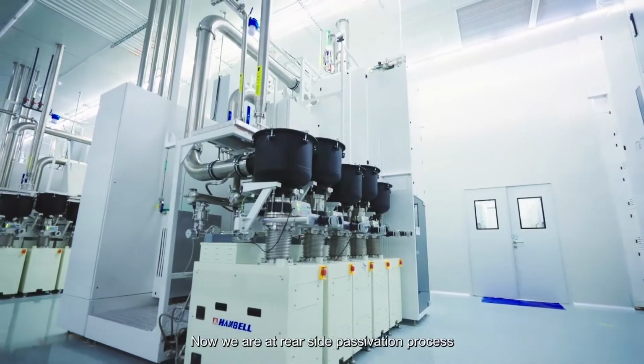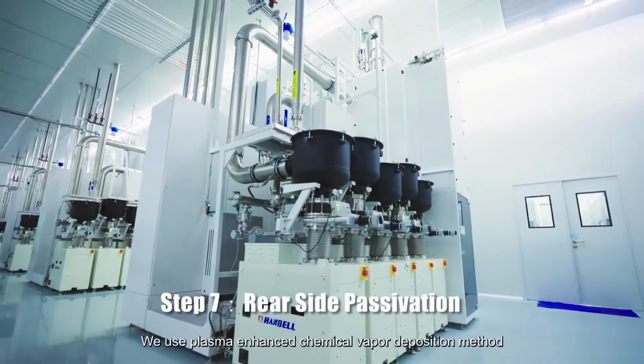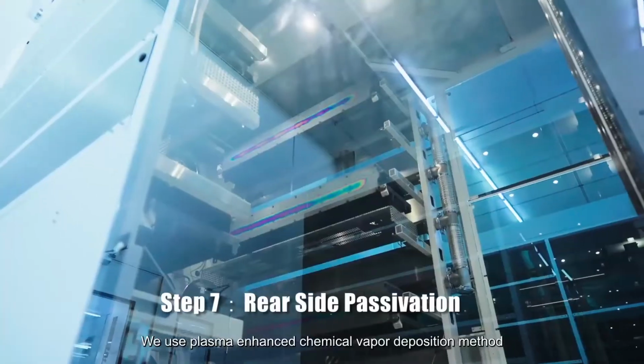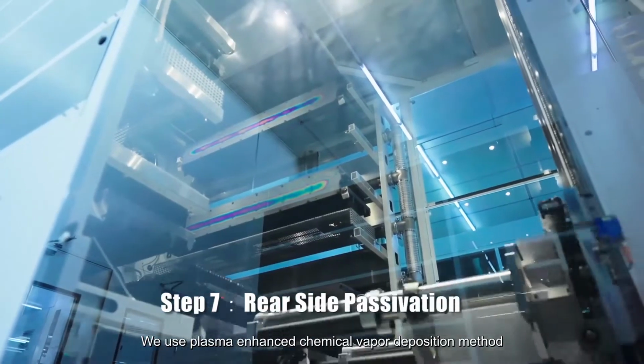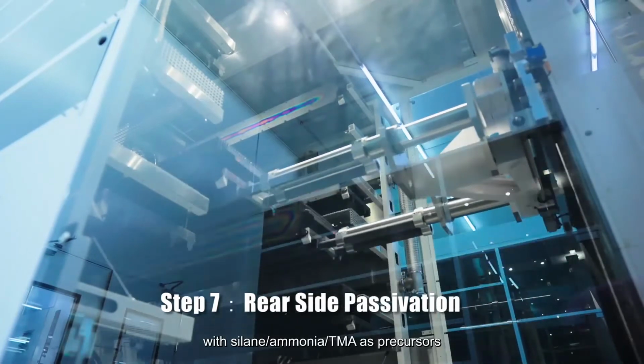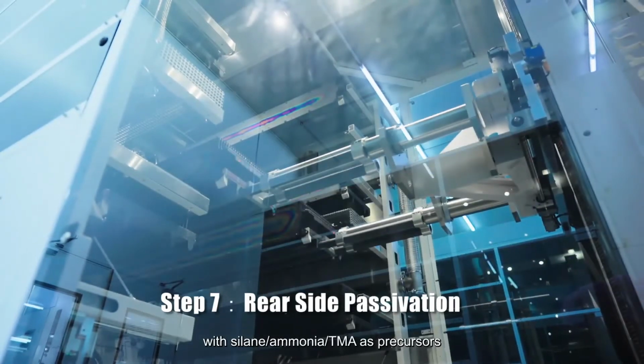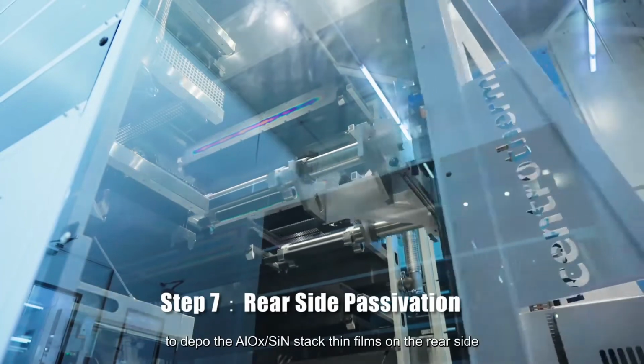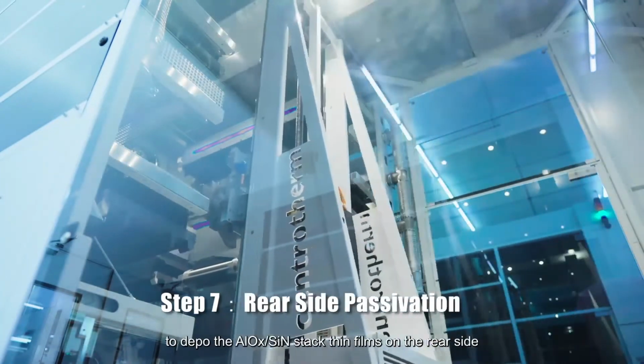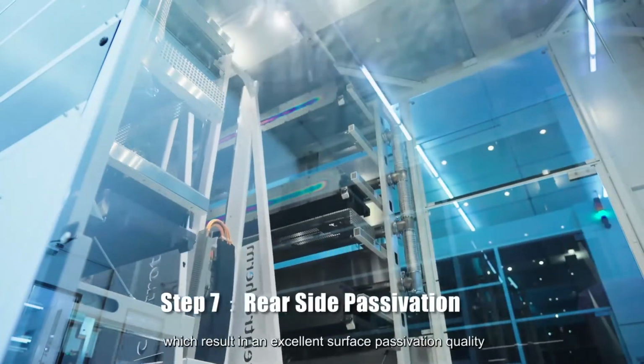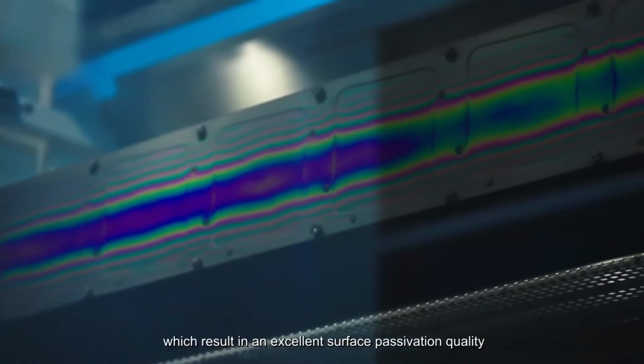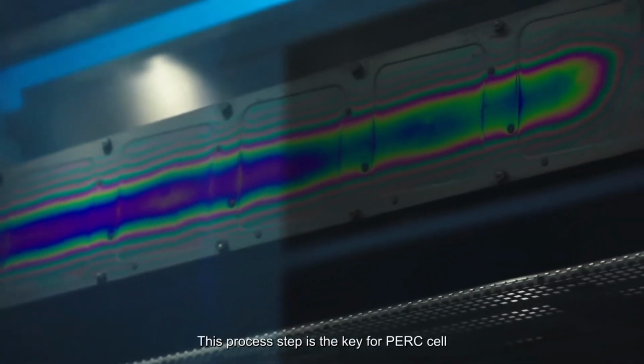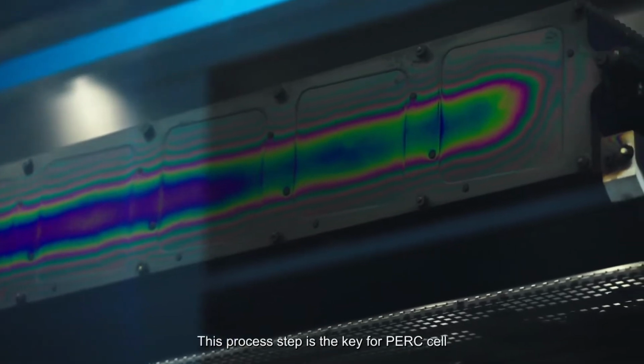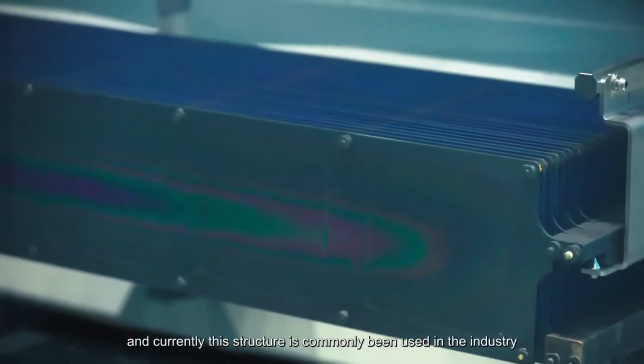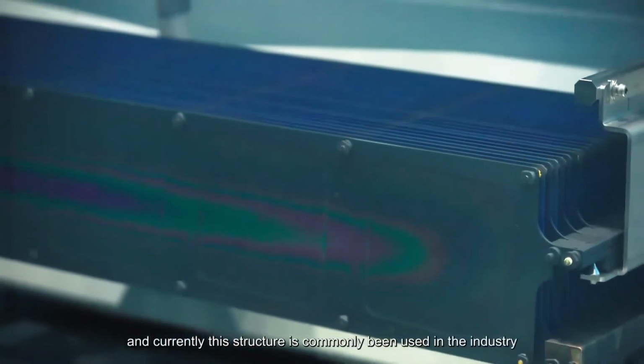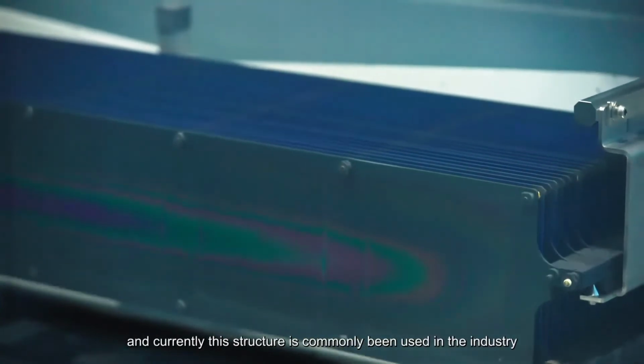Now we are at the rear side passivation process. We use the plasma enhanced chemical vapor deposition method with silane, ammonia, TMA as precursors to deposit aluminum oxide and silicon nitride stacked thin films on the rear side, which result in an excellent surface passivation quality. This process step is the key for PERC cells and currently this structure is commonly used in the industry.